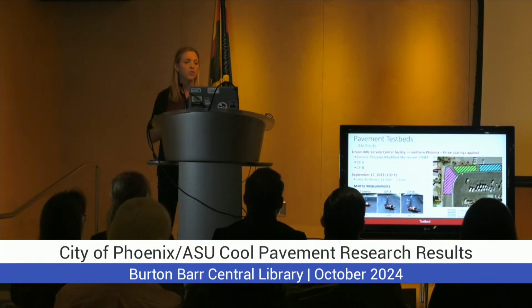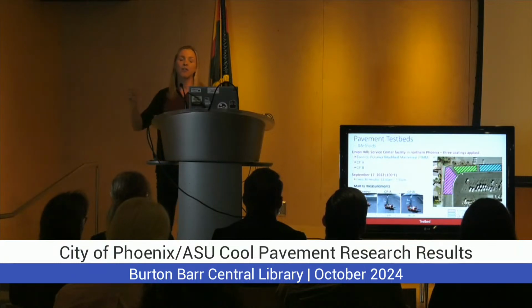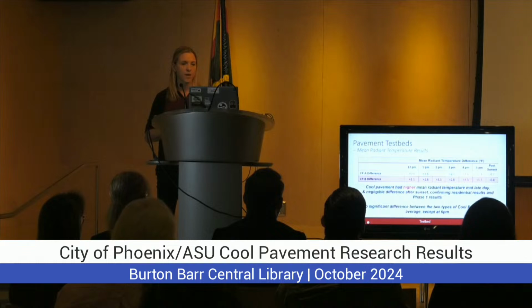And we did MaRTy measurements every 30 minutes on September 17th, where we moved the MaRTy cart throughout to get these mean radiant temperature measurements, also did surface temperature, and then we also have these reflectivity measurements that show you the difference in reflection of the 3 surfaces we tested at the test bed. So with mean radiant temperature, very similar results again, and a negligible difference after sunset, but when we compare the 2 different types of cool pavements with this, there's no significant difference there.